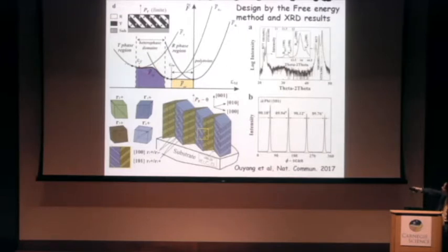But when you put it on a substrate, there's a certain misfit range where the mixed phase becomes more stable, right? I don't need to say more about it. People already know it in the bismuth ferrite case. But you can see when the misfit strain is higher, close to the self-strain of the tetragonal phase, the dominant polydomain structure will be a tetragonal-rhombohedral mixed phase, just like in the case of bismuth ferrite.